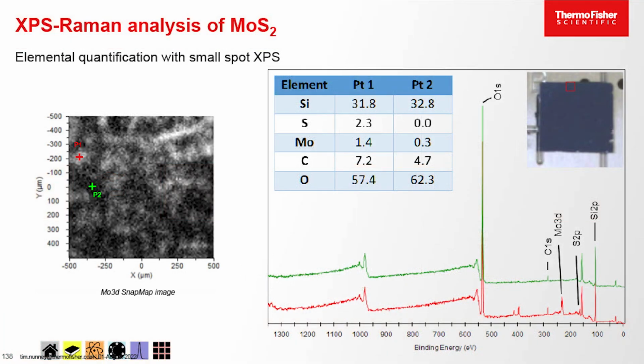So this was a commercially bought sample, so we wanted some of these 2D materials, so we bought what was supposed to be a wafer covered with molybdenum disulfide, just a single atomic layer of MoS2 across the surface. And what we found when we analysed it was it's really, really patchy. So this is the molybdenum snap map, and where it's light is where we've got a strong molybdenum signal. Where it's dark, we've got a weak molybdenum signal. And it's never going to be super strong because it's only one atomic layer, but it's really, really patchy. And in some areas, we've got no molybdenum at all. So we thought about asking for our money back, and then we thought about maybe trying to use this as a nice example to use in seminars like this one.